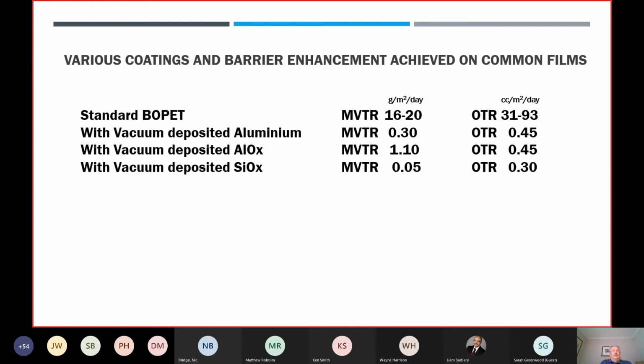So what I thought it would be interesting to do was to actually show you what some of these barrier coatings do to films in terms of improving the barrier of those films. So if you look at a standard polyester film, moisture barrier of 16 to 20, and oxygen barrier 31 to 93. And don't take these as tablets of stone. You go to lots of people's websites, and they all quote slightly different figures and slightly different conditions for testing. But in the main, they give you the flavour for what you can achieve.